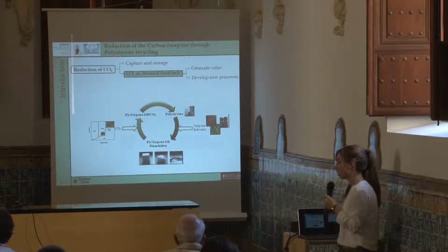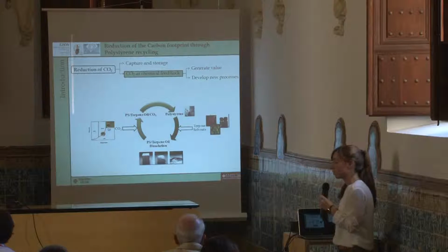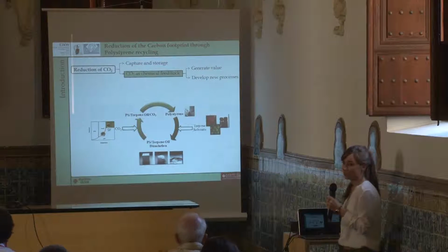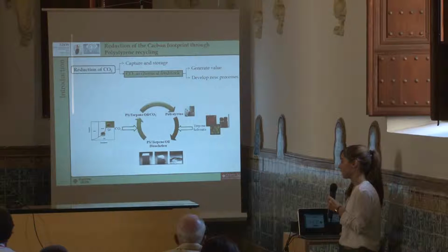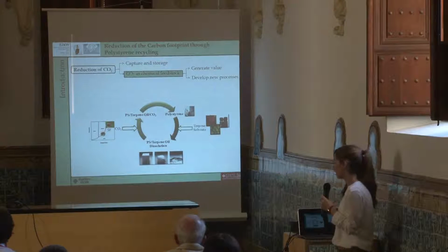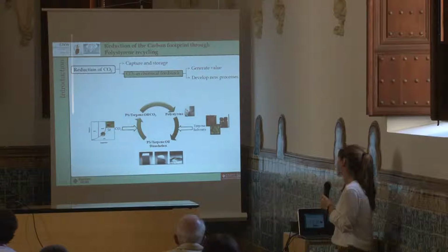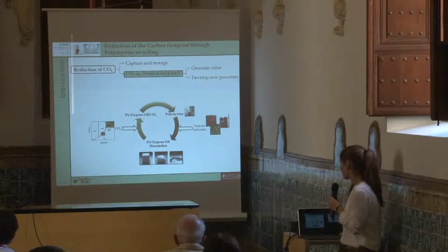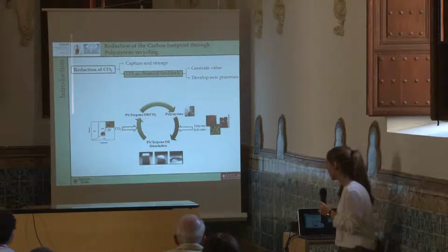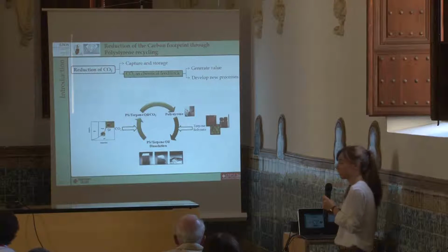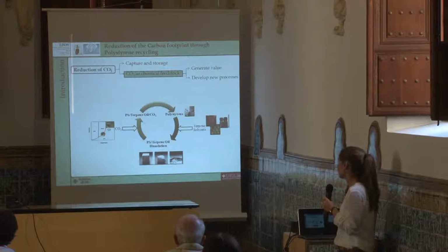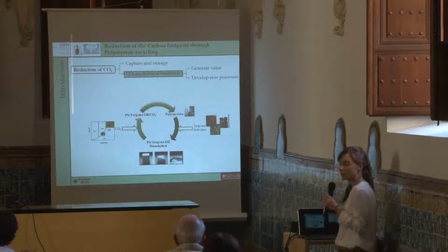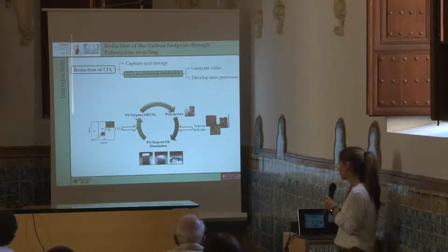Polystyrene is soluble in aromatics, but the use of this kind of solvents could prevent further application in food packaging or similar uses. So we propose the use of terpene solvents, particularly in this study, limonene, because they are obtained from nature, so they are renewable. And also, an important point is that we can observe an important volume reduction during the dissolution.